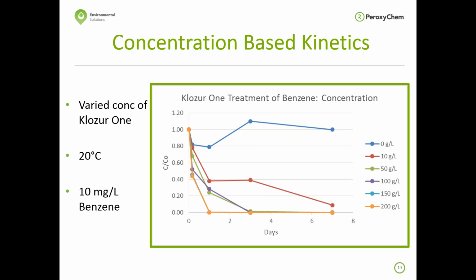And what you can see is that within 1 day, the 150 and 200 gram per liter systems took 10 milligram per liter benzene to non-detect within the 1 day time frame. By the 3 day time point, the 100 gram per liter system was non-detect. The 50 gram per liter was almost there.